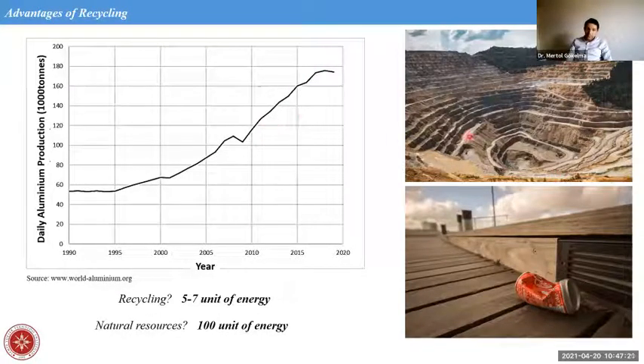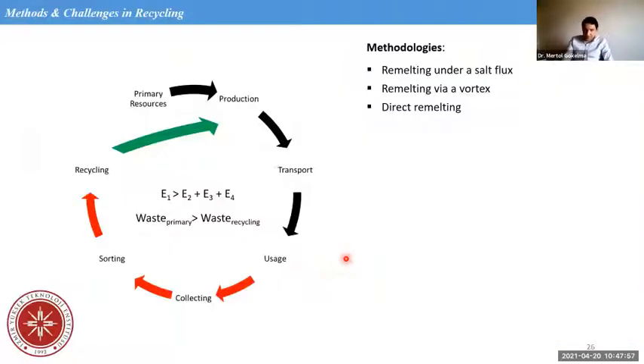And this increase means we consume our primary natural sources, and they are limited. It also means we produce a lot of scrap. This increase also means an increase in scrap. And there recycling comes into the game and says, if you do recycling, you need 5 to 7 units of energy, maybe 5 to 10 maximum, but natural sources need 100 units of energy. The reason is that when we do primary production and use primary sources, it goes for transport and usage, and then it is scrap.